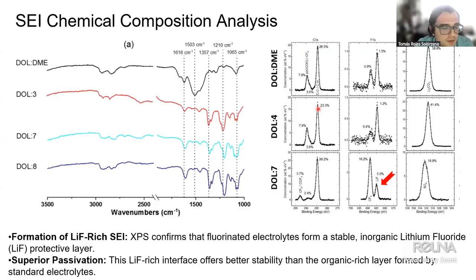These also are some of the experimental results from XPS and infrared spectrum, and the experimental results in most cases also give us a hint that if we take a look here at the 1s orbitals of the fluorine, there is formation of lithium fluoride, so we have a pretty good idea that it is related to lithium fluoride in the formation of the SEI.